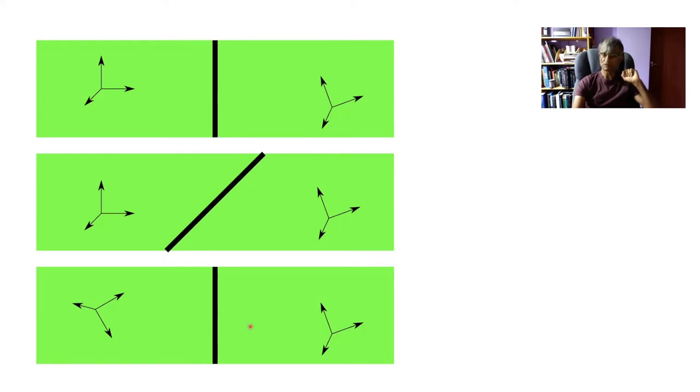So each interface will have 5 degrees of freedom, three of them defining the orientation relationship between the two crystals, and two for the interface normal. Whenever we do these operations, the structure of the interface will change.